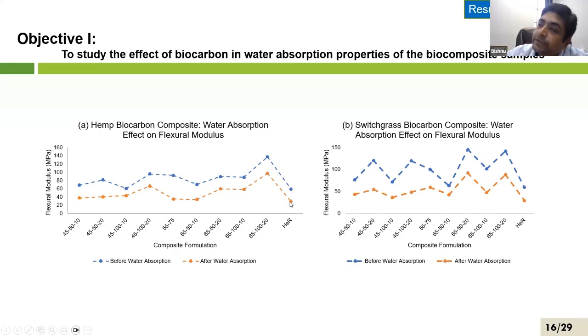Yeah. So what we have found is, we did the mechanical test after 5 weeks of water absorption, then we did a mechanical test on that sample to see what the flexural modulus is and how it changes. So definitely, when it absorbs the moisture, you are going to see reduced mechanical properties. Here, if you just look at the hemp resin, before moisture absorption, they are here. After moisture absorption, the properties went down.